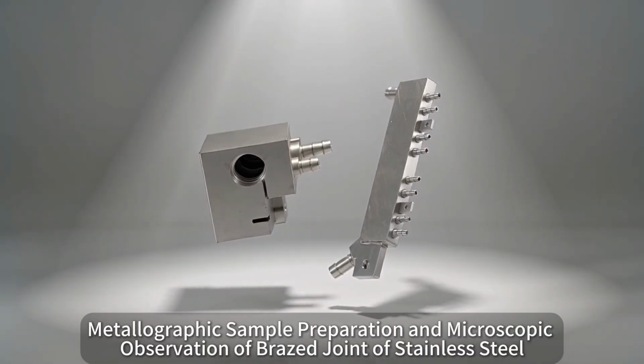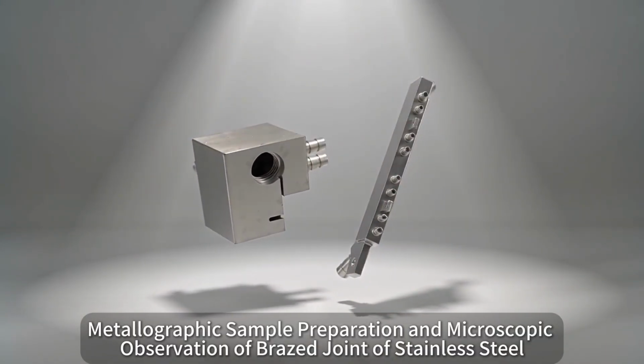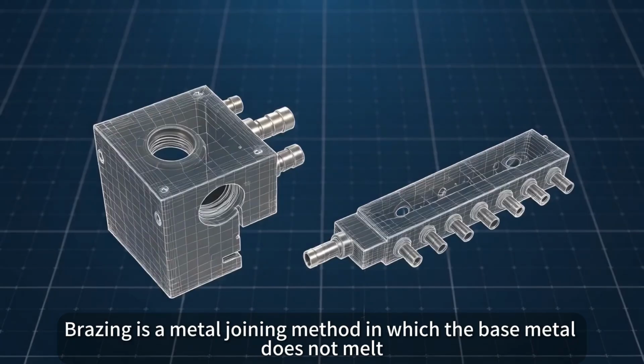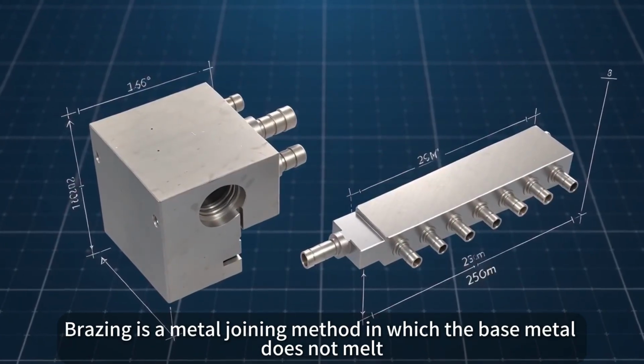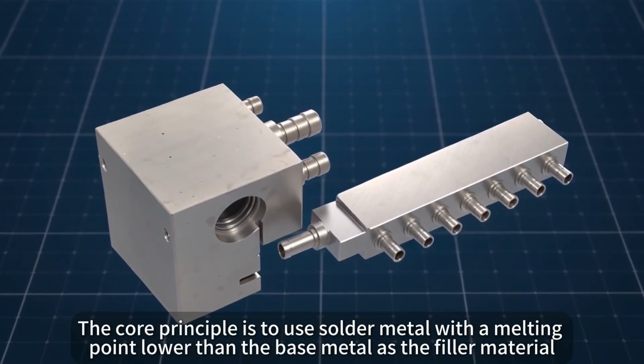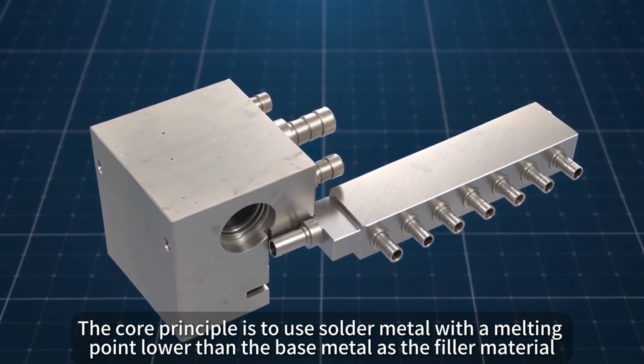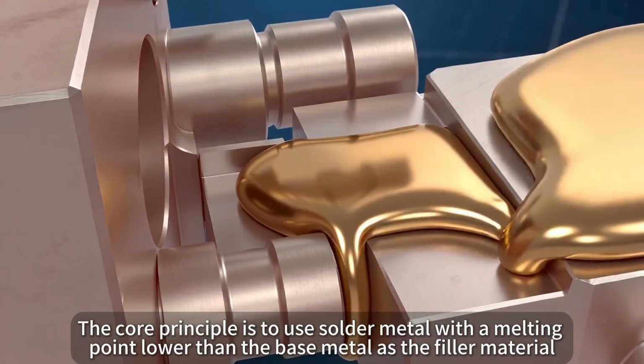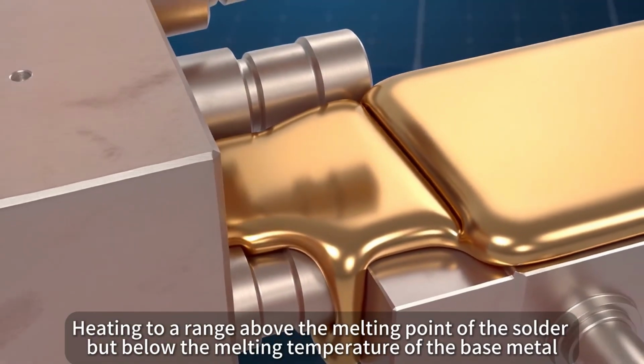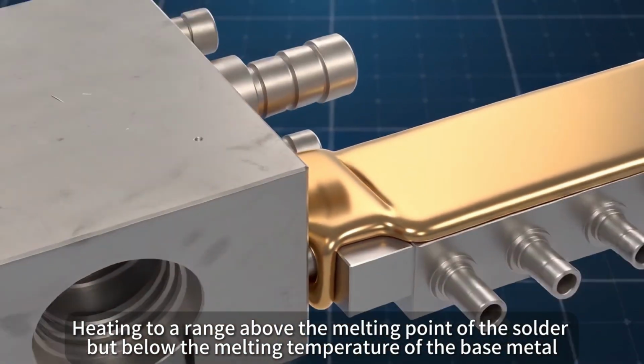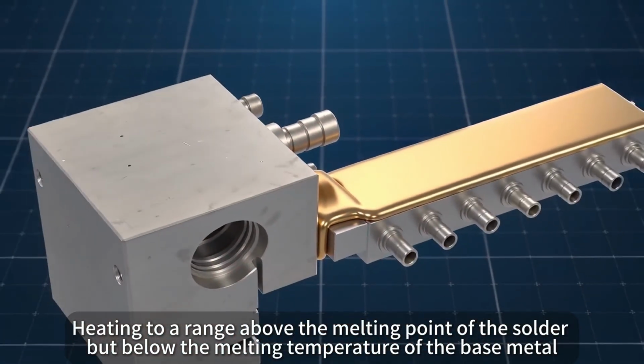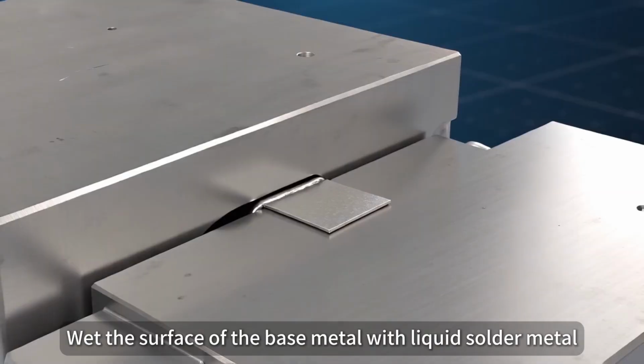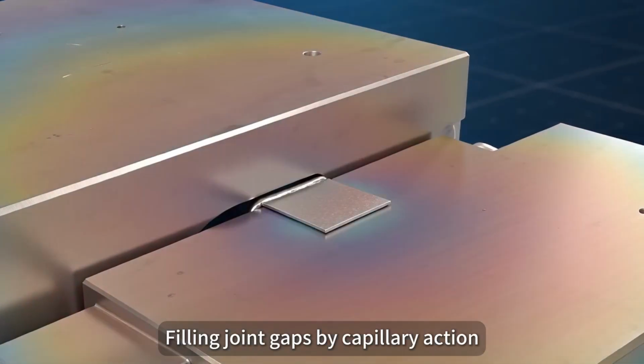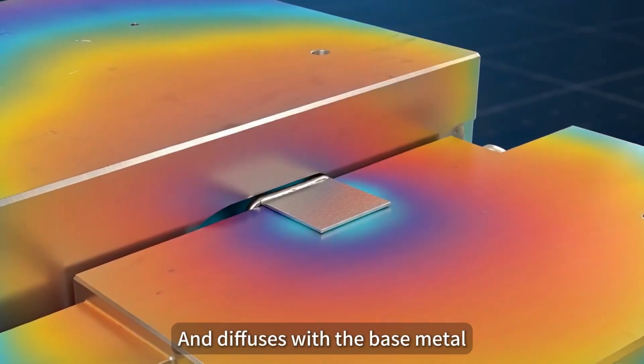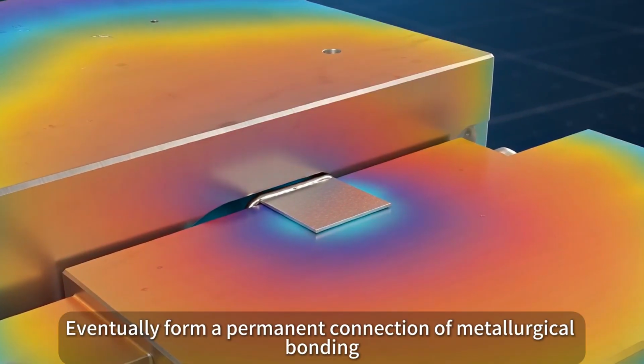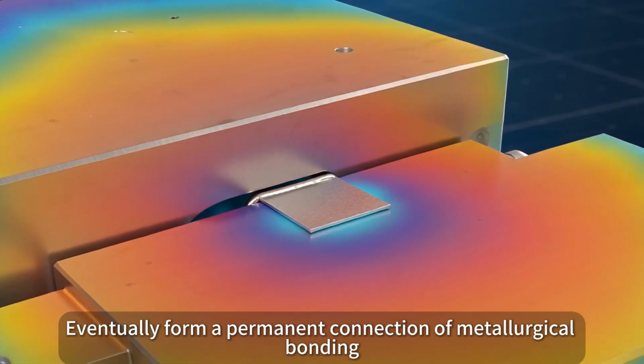Metallographic sample preparation and microscopic observation of a brazed joint of stainless steel. Brazing is a metal joining method in which the base metal does not melt. The core principle is to use solder metal with a melting point lower than the base metal as the filler material, heating to a range above the melting point of the solder but below the melting temperature of the base metal. Liquid solder metal wets the surface of the base metal, fills joint gaps by capillary action, and diffuses with the base metal, eventually forming a permanent connection of metallurgical bonding.